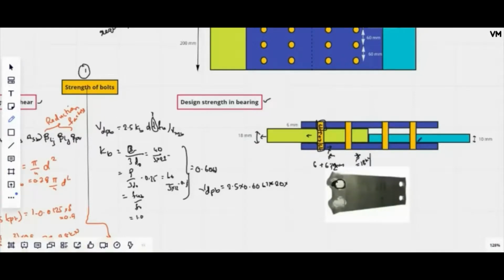If we consider the next part of the plate and apply the same approach, when we take out this portion, if the force is in this direction, the bolt will experience bearing in this direction, and in these two plates it will experience bearing in the other direction. If I take this direction, I will get the thickness as 12 mm, as it is 6 mm from here and 6 mm from here. But when I consider this one, I get the bearing thickness as 10 mm. So I have to take the minimum of all four. The minimum of all four is 10 mm.